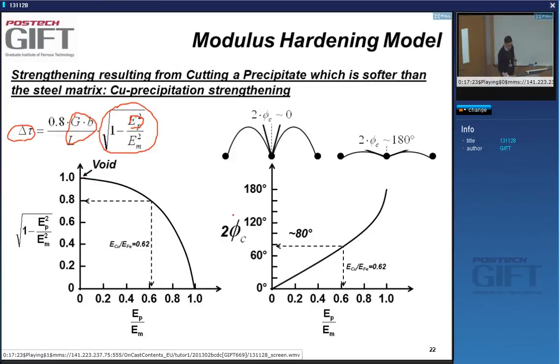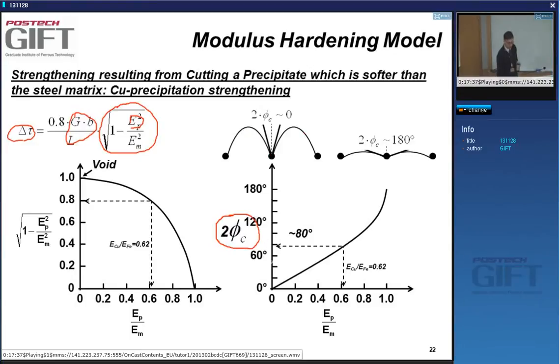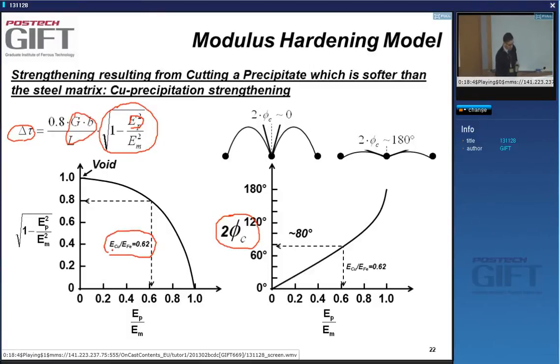From the same model you can get the critical breakaway angle. For a very soft precipitate, at breakaway the angle 2φ_c is close to zero. Whereas if the particle has a modulus very close to that of the matrix, there's not much strengthening and the breakaway angle is very large. For copper and iron, the ratio of moduli is about 0.62, so we expect considerable strengthening and a breakaway angle around 80 degrees.